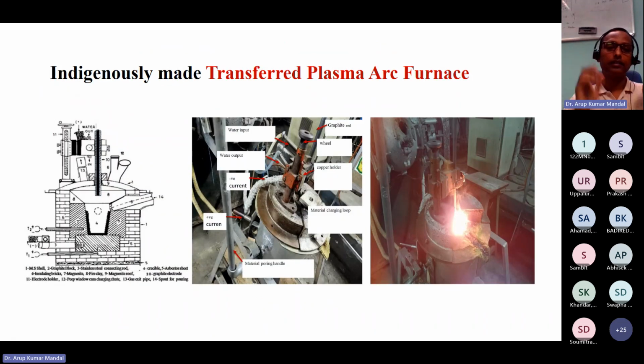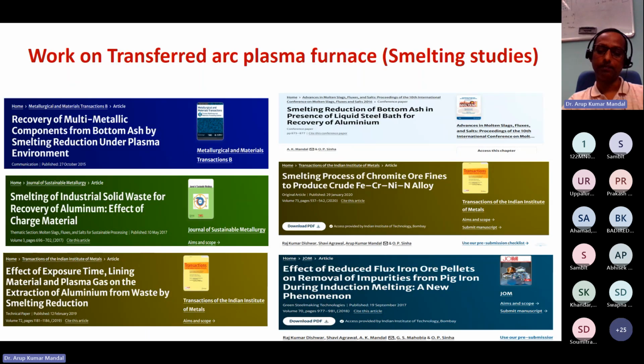So here, this picture is an indigenously fabricated transferred arc plasma furnace. This setup is at NIT Durgapur, where we do different smelting operation experiments using this furnace. We have recovered multimetallic components from waste materials, thermal power plant waste materials like fly ash and bottom ash, by smelting reduction under this plasma environment. We have recovered the aluminium from the waste material by this smelting reduction route by this plasma.